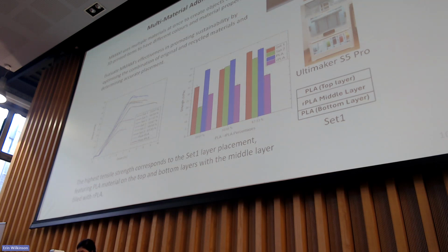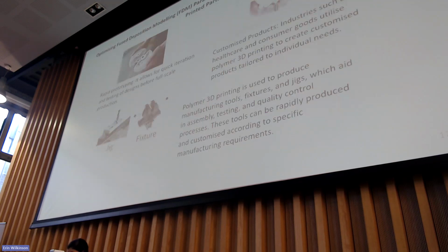Basically, the aim for this research was to evaluate the effectiveness of multi-material 3D printing in promoting sustainability by optimizing the combination of original and recycled material. And we used different combinations. We used different placements, and we used a different percentage of the original and the recycled material. And we found out that by combining a certain percentage of the recycled material with the original material, we can still get the same strength as we can get from the original samples, which is also very good.